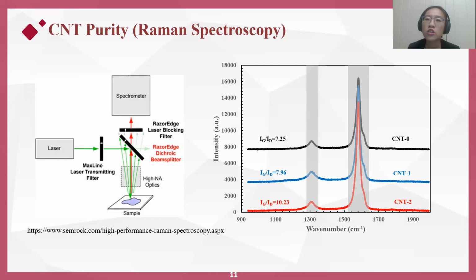Under identical conditions, the addition of water increased this ratio from 7.25 all the way up to 10.23. This CNT quality improvement could possibly be attributed to the effectiveness of catalyst cleaning by amorphous carbon removal. We also noted that the G band exhibited an asymmetric line shape with a weak peak appearing at 1590 or 1595 per centimeter. This is likely associated with the large amount of multi-wall CNTs, due to the diameter variations among different tubes in a typical CNT assembly. This asymmetric feature became less conspicuous as the water concentration increases from top to bottom, suggesting a narrower diameter distribution of multi-wall CNTs with fewer disorders.